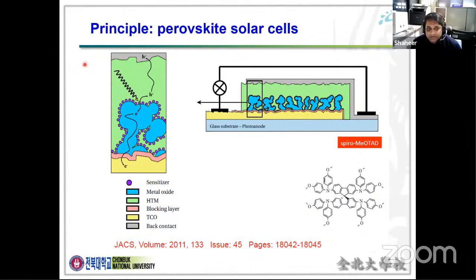So when the light illuminates the solar cell, the sensitizer, that is the perovskite, absorbs the light and injects one electron to the conduction band of TiO2, and this electron travels to the outer circuit and then generates the electricity. And the remaining holes are collected by the hole transporting materials and transported to the top layer. So this is the simple mechanism, which is very similar to the solid state dye-sensitized solar cell.